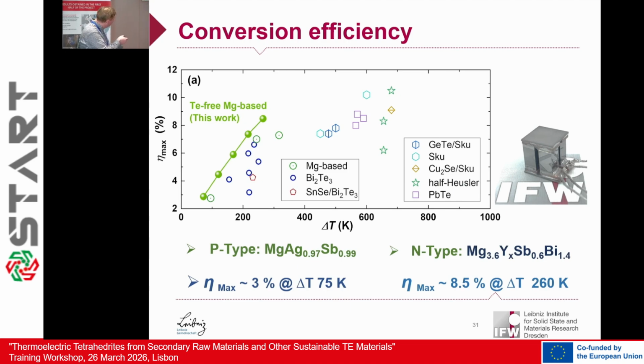Okay, what you also have here are some data points from other modules with higher temperature materials like skutterudites, half-Heuslers, for example. You can see efficiency is not higher because they're, on the other hand, performing very weakly at low temperature. So you can only harvest the heat from the higher temperature, but not from the lower. But if you would combine magnesium antimonide with, for example, a skutterudite-based module or a half-Heusler, most likely you can reach, I think, efficiencies in the range of 15 to 20%.